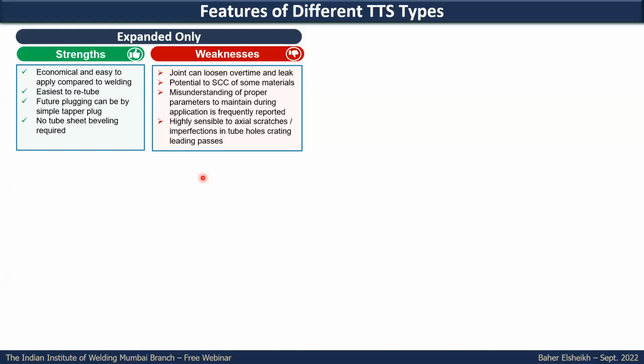But in the weaknesses, it can loosen over time, especially under cyclic load, temperature, or high differential pressure between the two sides. And in some cases, there is potential for stress corrosion cracking if you have high residual stresses in the application. That's why for some materials, as we will see later, you have to limit to what extent the tube will be expanded. And it is not something strange, as there are frequent reports that the proper parameters need to be maintained during the expansion, which are somehow misunderstood, leading in some cases to frequent leaking or issues in the heat exchanger.